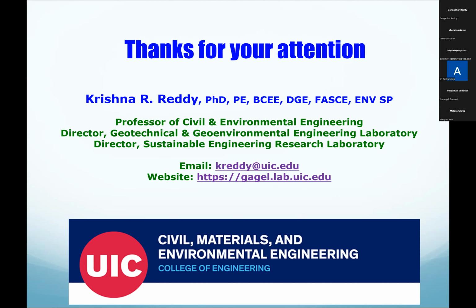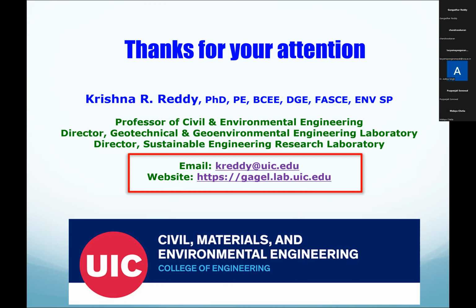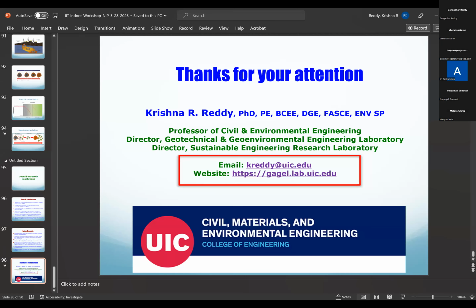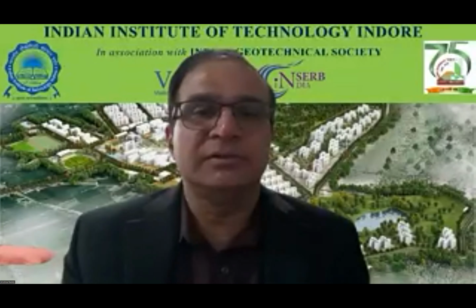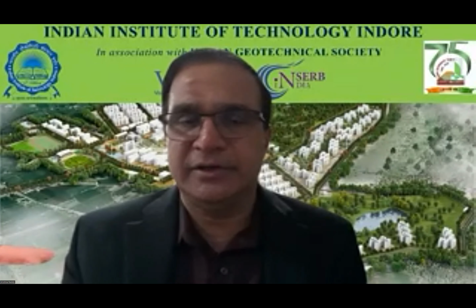our results were used by US EPA and some other industrial partners to apply in the field. I didn't mention another factor, which is pulsing, even with the lactate modified iron particles. Instead of putting them under constant pressure, with pulsing pressure, we found out that it can enhance the transport. So the results are actually used by industry for field applications. We are not involved in it. We contributed to the science and fundamentals and proposed the solution. Somebody else was actually trying to use it out in the field. That makes me happy because somebody is actually using your results for actual field applications. So I wanted to showcase how research is done.